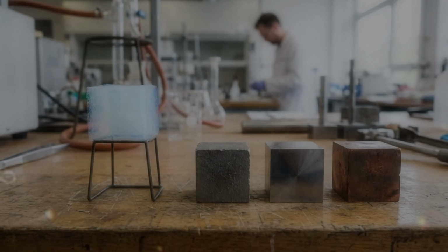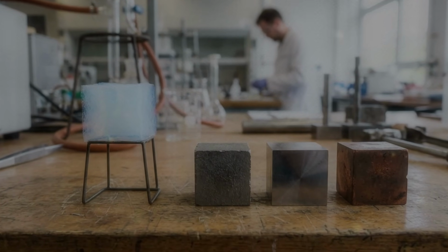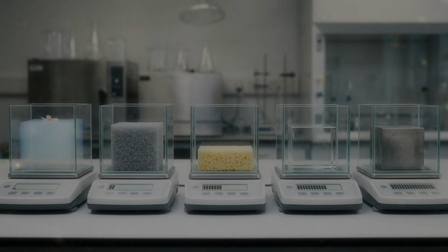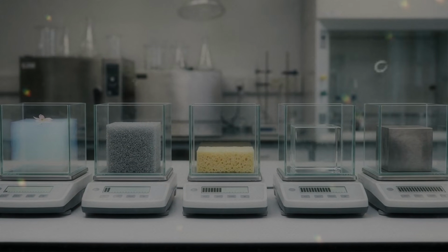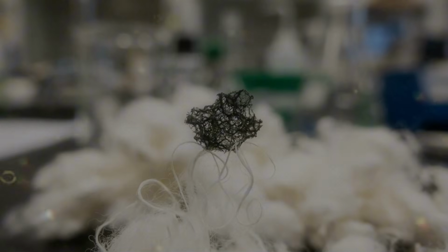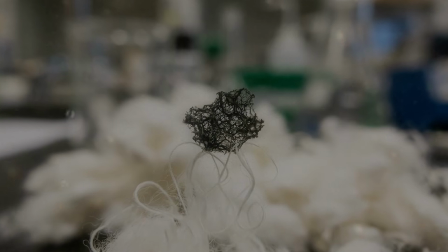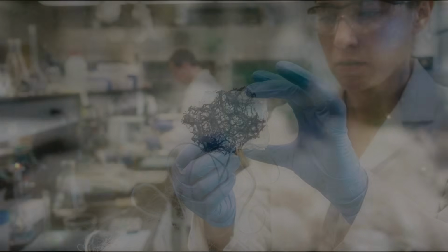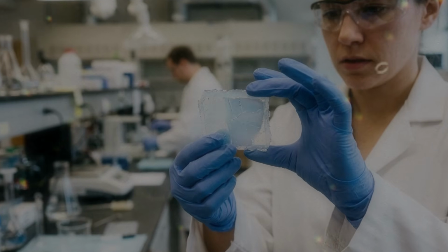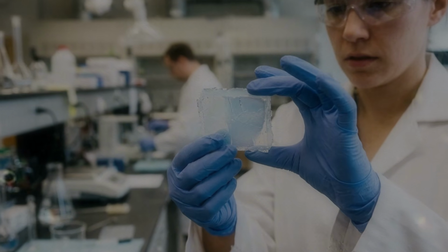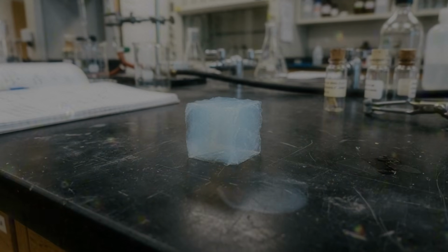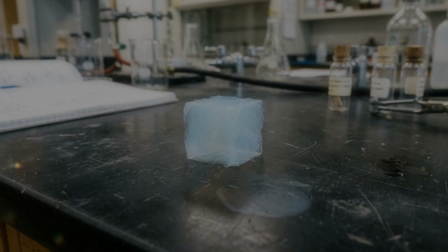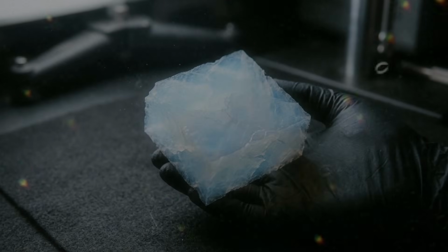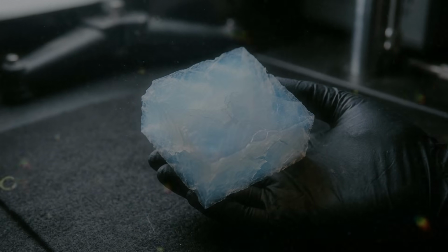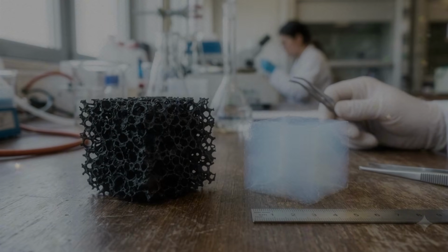Graphene-based aerogels approach this problem with thin carbon sheets. Graphene itself consists of carbon atoms joined in a single layer. A perfect sheet is extremely thin and can be very strong within its plane. It also conducts electricity and heat effectively. Turning that sheet into a three-dimensional aerogel changes the situation. Individual sheets can bend, wrinkle, and stack together. If they collapse into a dense pile, much of the open space and accessible surface is lost. Researchers therefore try to connect or separate the sheets so they form a stable network. The finished structure may resemble a foam, with walls made from overlapping layers of graphene-based material.